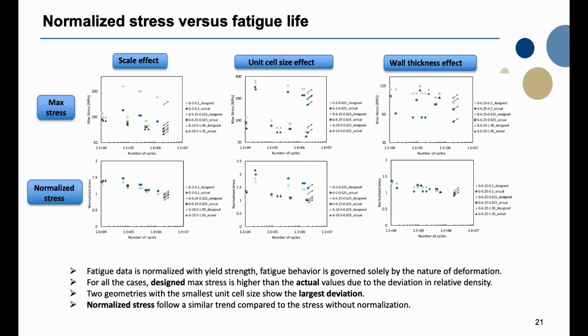So we also have the normalized stress versus the fatigue life here. We have the maximum stress, and now we have the normalized stress. We can see that the fatigue data is normalized with the yield, and it's solely governed by the nature of the deformation. And we can see that the two geometries with the smallest unit cell size show the largest deviation, and the normalized stress follows a very similar trend compared to the stress without the normalization.